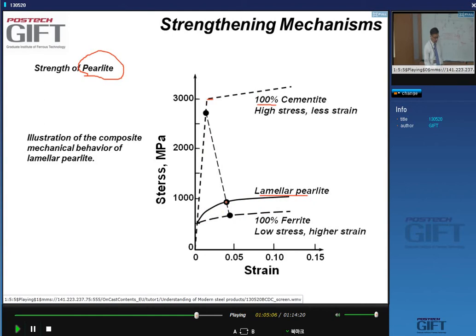In such a way that at any point on the stress-strain curve of this lamellar pearlite, I have stress and strain partitioning. That means that the two phases are not subjected to the stress and the strain of the pearlite, but they have very different stresses and strains. In particular, the very strong phase picks up most of the stress and undergoes very little deformation. And the reverse is true for the soft phase, which picks up most of the strain, the deformation, and much less stress.